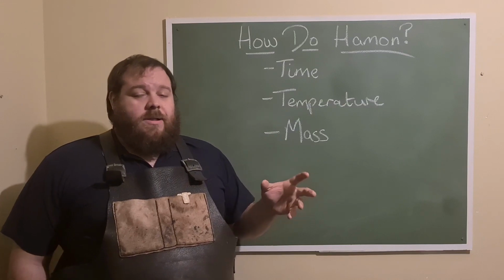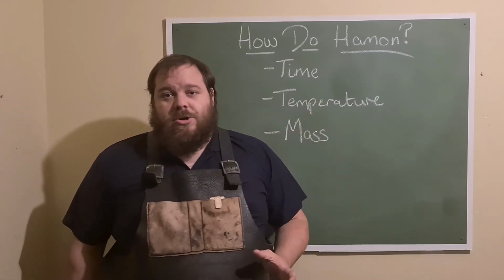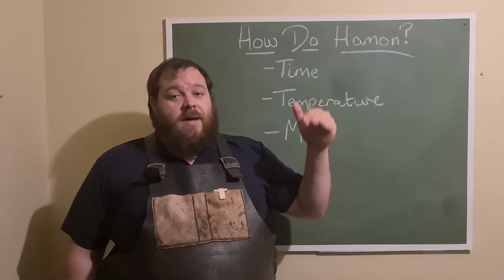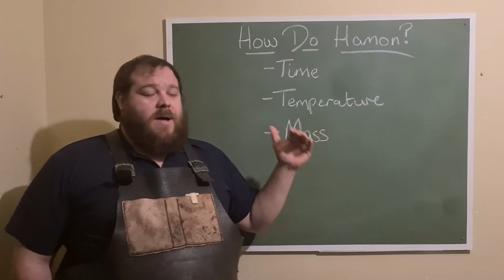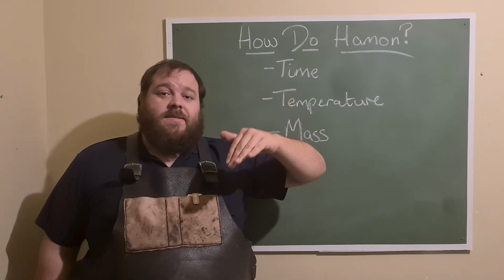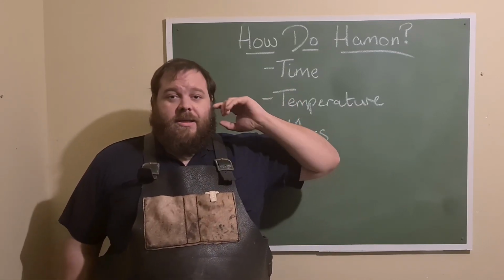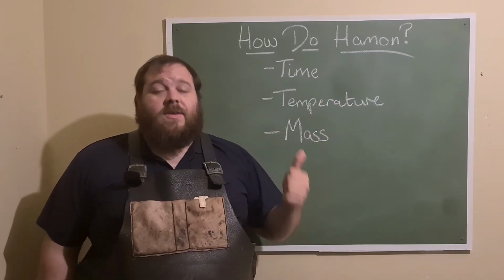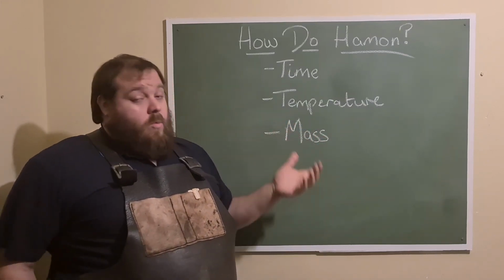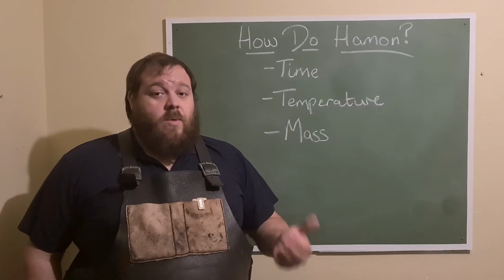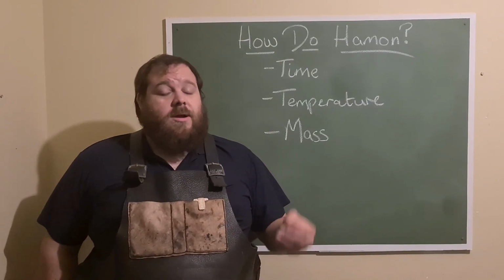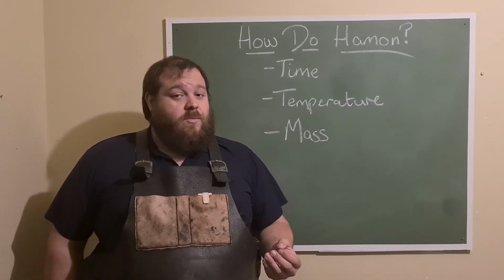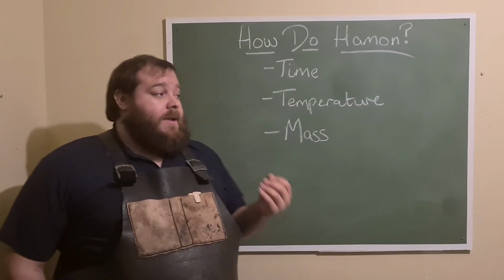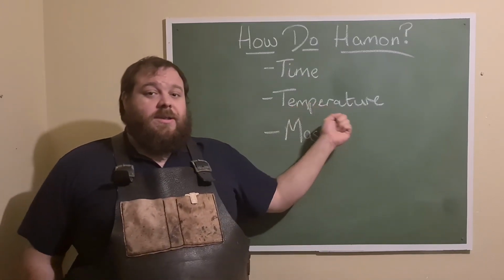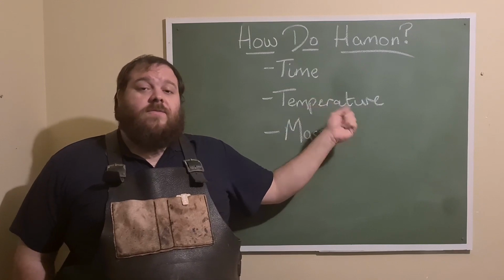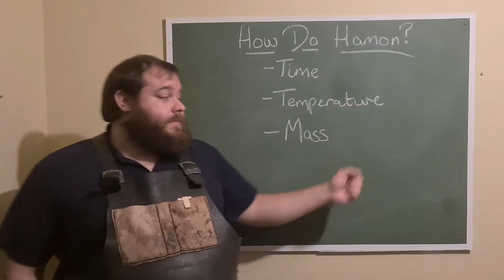And when I say cool it quickly, we don't need to get it down to room temperature quickly. What we need to do is get it past the martensite nose. We need to get it past the point at which martensite starts to form really quickly. And so that's why we use things like Parks 50 or Houghton's K or water. And this is why the Japanese quench in water. Now, they preheat their water. You should preheat your oil and your water if you're going to do a water quench. But the speed at which you bring that temperature down is going to affect how well your Hamon develops.